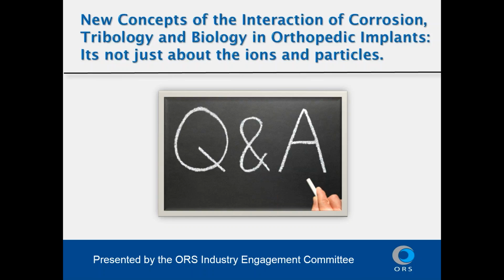Okay, so the last question for this webinar, with regard to cell apoptosis under cathodic potential, is it possible cells die due to large pH increases? Oh, it's certainly possible that it's oxygen depletion, it's possible that it's pH increase, and it's possible that it's these reactive oxygen intermediates. I think there have been studies that have looked at pH shifts. We've done some related to magnesium, and you can get pH shifts that are up into the 8s, maybe high 8s, maybe even low 9s, and cells will still remain viable over 2 hours, whereas under these electrochemical conditions, the cells die rapidly. Again, I haven't done the calculation to estimate the pH at that surface, but I don't believe it would rise to that level in these solutions.